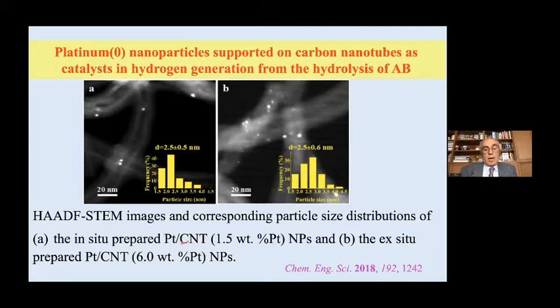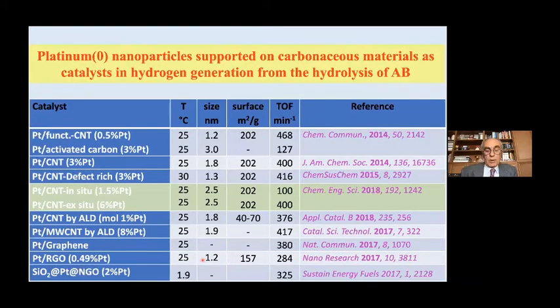However, the in situ and the ex situ prepared nanoparticles have different loading, 1.5% platinum or 6.0% platinum loading, and therefore the activities are expected to be different, of course. And indeed, they are different. The ex situ provides 400 reciprocal minute, while the in situ only 100. But something is weird here, so it should be opposite actually. And therefore, I don't want to rely on that result. Anyway, the ex situ and the in situ are different.